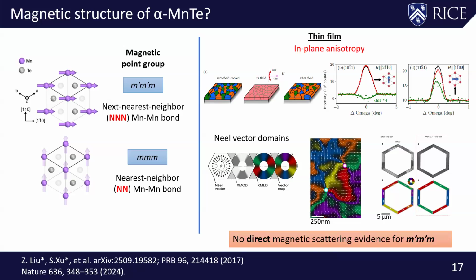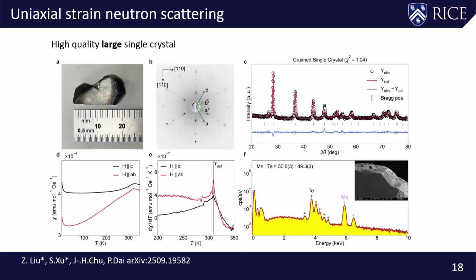So yes, there are a bunch of measurements. People have published papers looking at the different magnetic domains. You can clearly see three different magnetic domains, and they plot them out with an additional magnetic field along the c-axis. You can change the magnetic domain along the c-axis because you can have up, down, down, up, right? But the central issue is that you cannot actually separate which magnetic structure is correct.